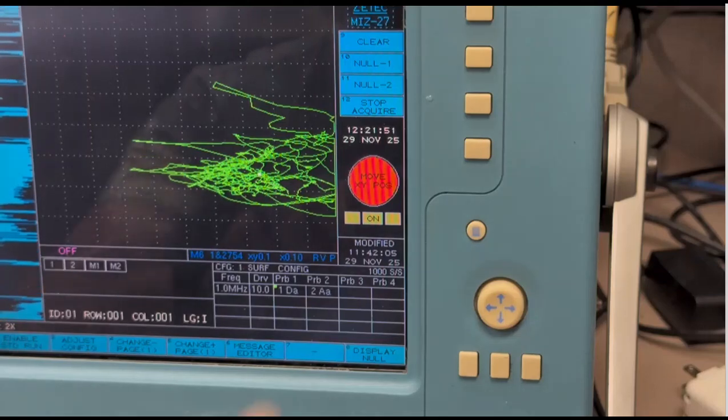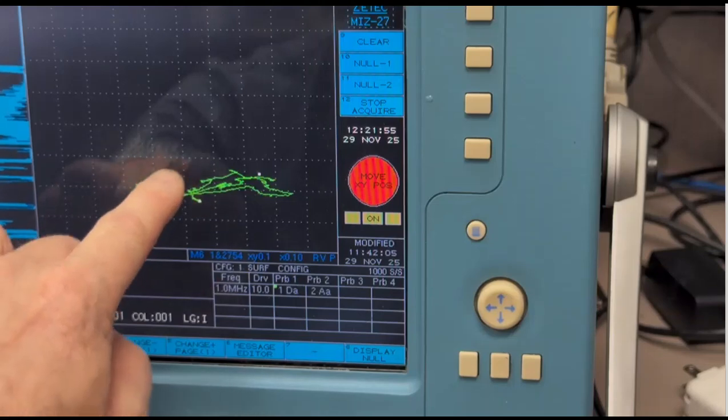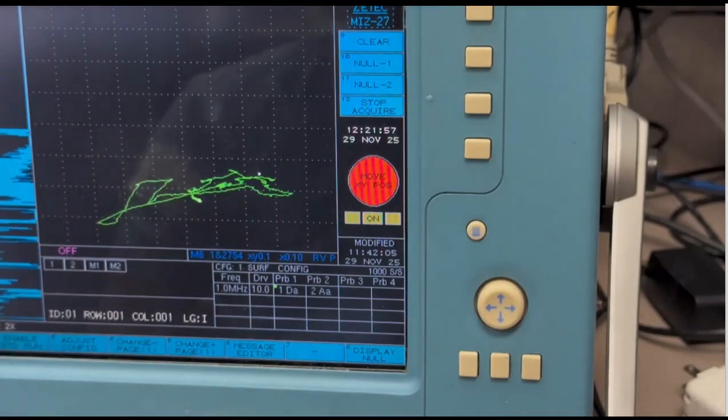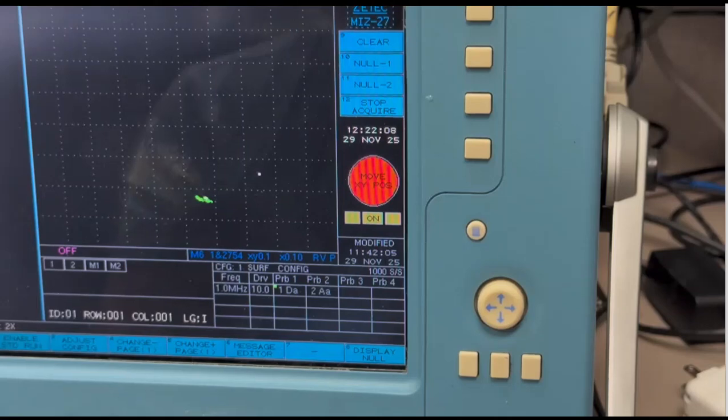We have extreme phase lag. That's why it's tricky to see it. That's your signal right there. So that's one division. Now it's like 120 degrees. So obviously the farther you go below the surface, you're going to have a lot more phase lag. It's going to rotate clockwise. And the amplitude goes way down.